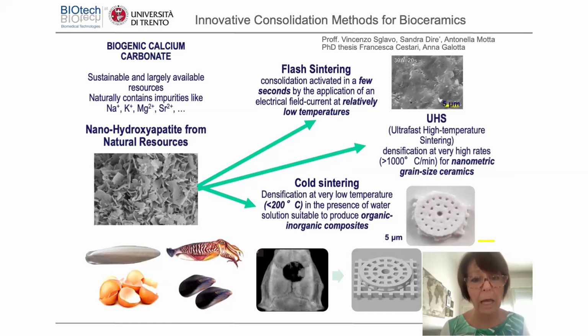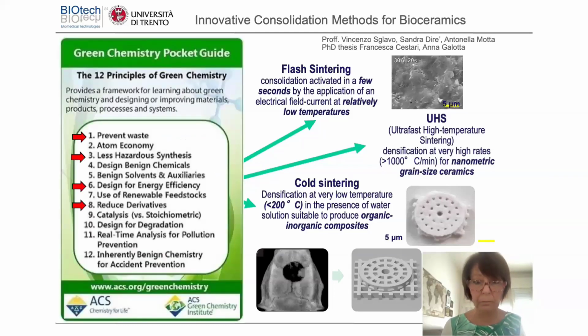of the final material. After the sintering, a powder is obtained, and this powder can be printed to obtain a scaffold for bone regeneration mainly, and thanks to the printability, several architectures can be obtained, even with some gradient, to approach applications such as, for example, the osteochondral defect.